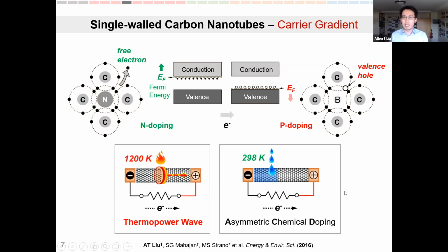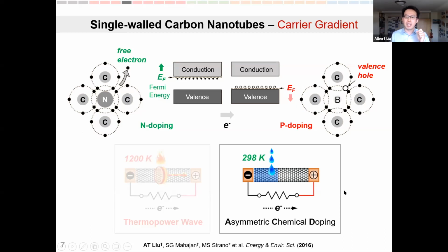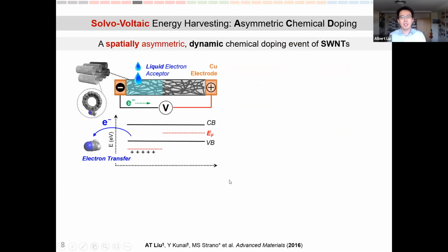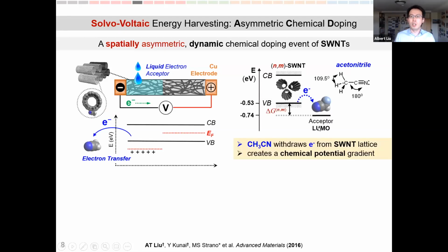Given the time limitation today, I can only focus on one, which is asymmetric chemical doping, that is more relevant for colloidal electronics anyway. Asymmetric chemical doping, as its name suggests, is the spatially asymmetric doping event rendered by the solvent molecule. If you can place the lowest unoccupied molecular orbital, or LUMO level, of your solvent molecule close to the valence band of your electron donor, the carbon nanotube, it's possible for electrons to transfer from the donor carbon nanotube to the receiver solvent molecule. In this case, it's acetonitrile.